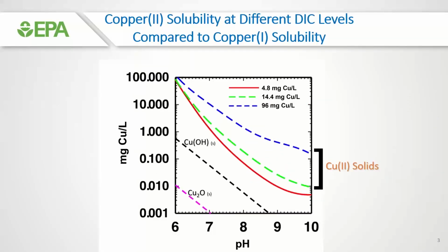I'm going to start out where I start all the talks, and that's talking about copper 1 versus copper 2 chemistry. So this is just a solubility diagram showing the solubility of copper 1 solids. So copper is in 2 oxidation forms in water, copper 1 and copper 2. The point here is, though, that copper 1 solubility is quite low relative to copper 2 solubility, which is represented in the lines here as a function of pH at different dissolved inorganic carbon concentrations. And the point here is simply that when we're concerned about copper levels, we're concerned about copper 2 chemistry.